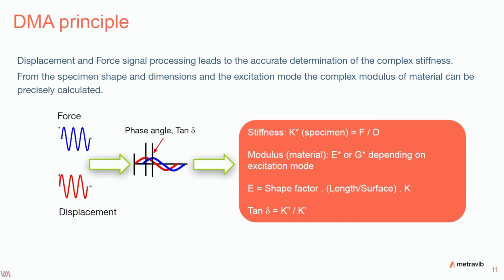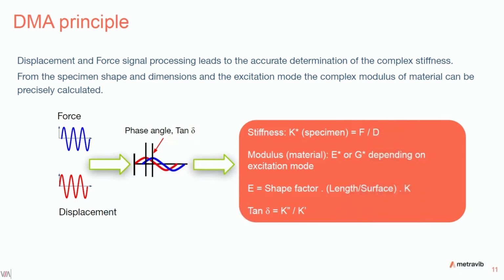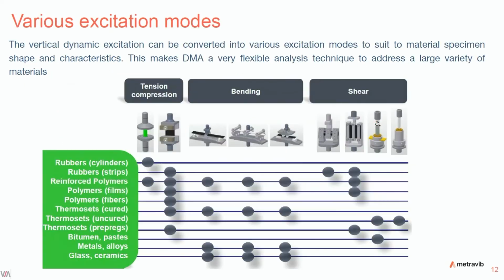and from the shape and dimensions of the specimen, we can compute the modulus: Young's modulus if you work in tension-compression, or shear modulus if you work in shear excitation. Tangent delta, representing the damping properties of your material, is just K double prime divided by K prime, or E double prime divided by E prime, just to give you the example.